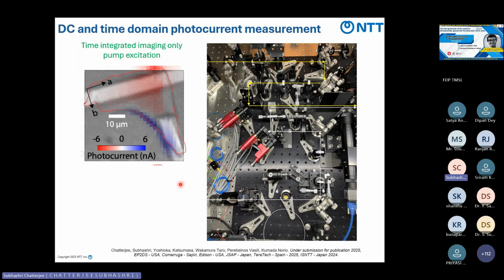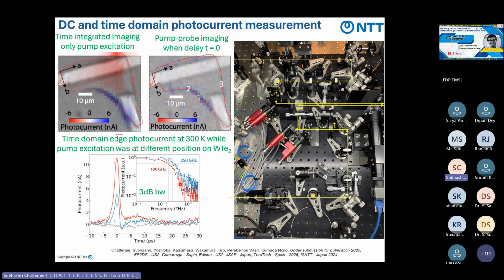Next, we tried our own setup with a time domain photocurrent measurement, and what we see is a very very fast signal from WTe2, around 180 to 250. If we change the position of the incident light, we can still see this fast signal.